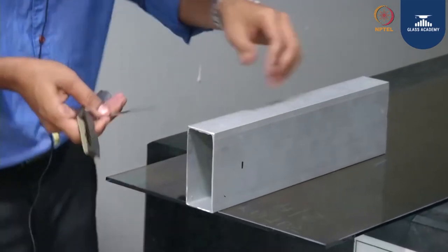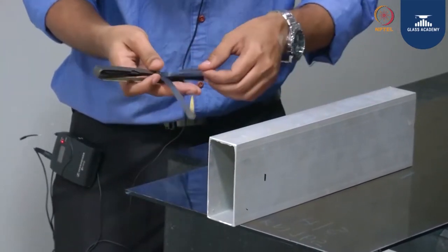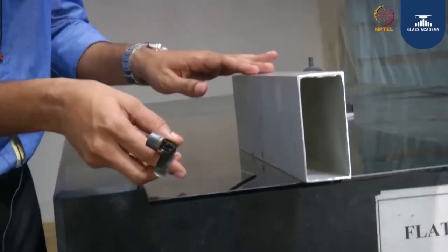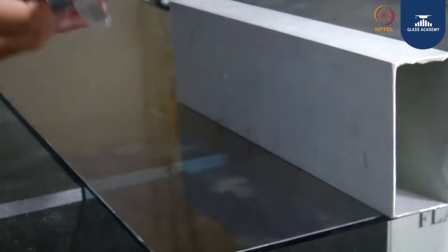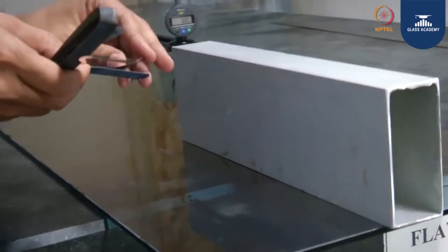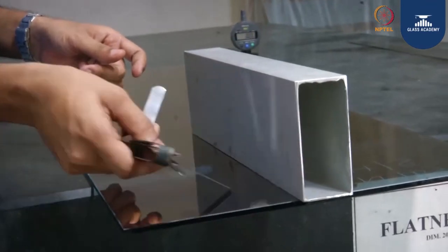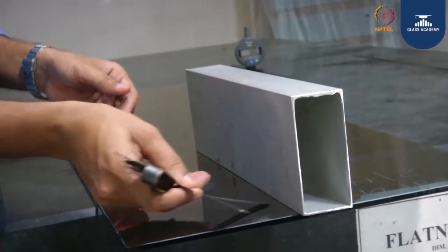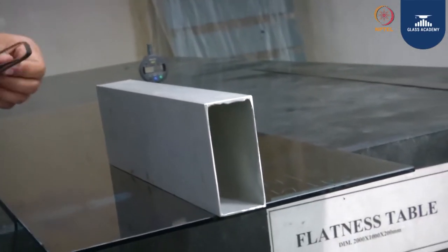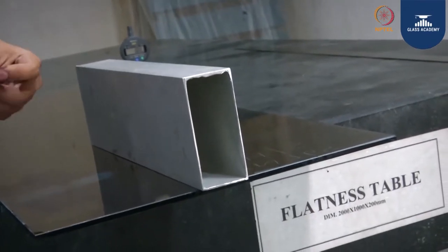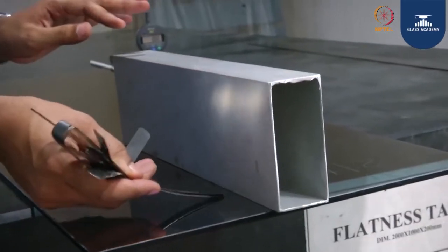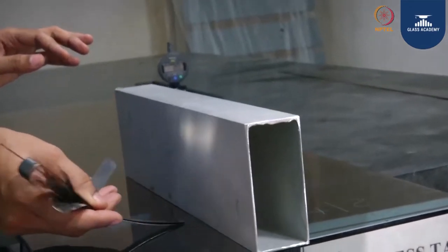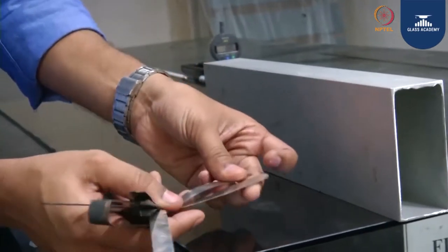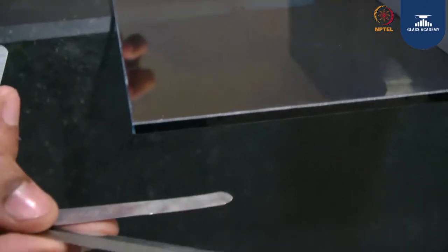Now I am trying to insert the feeler gauges. Now we are going to insert the feeler gauge readings into the glass surface. Whichever scale is not going in, that will indicate your roller wave, sorry, edge lift in the glass. You see, this reading is not going. So this is how you measure the edge lift in the glass. So it is 0.19 mm.